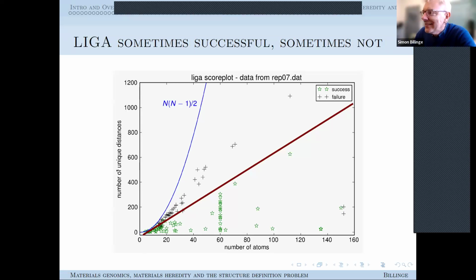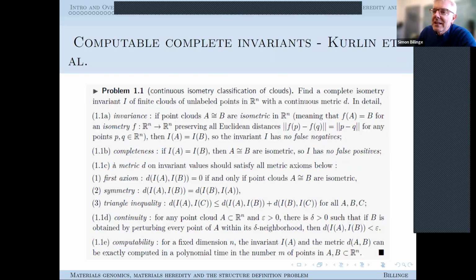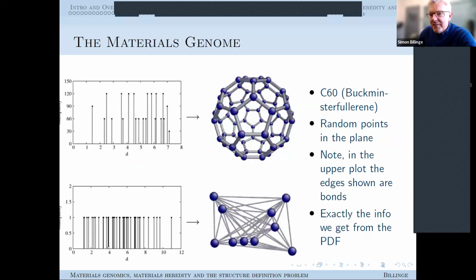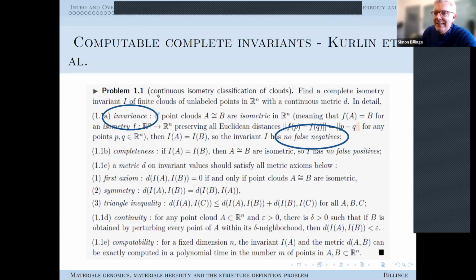And in the end, we felt that it was something to do with an information theoretic problem, that when you have a large number of unique distances, if you could measure that with perfect resolution, you would have more information in your input data than if you had a small number of unique distances. But when you measure it with finite resolution, these distances start to overlap. So I can quickly go back to this generic graph. This histogram down here has many more distances than that one. So this one down here has more information. But if I do a measurement of this with a broad resolution function, then I'll end up with, largely speaking, just a horizontal line here. Whereas here, I'll have one which has a lot of ups and downs in it. That's exactly what the data look like.